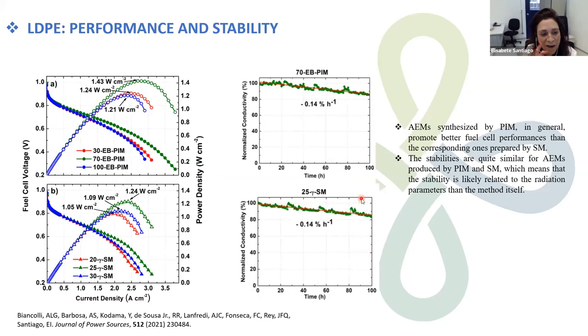So in terms of performance and stability, we have observed better performance for materials obtained from electron beam, I mean pre-irradiation, in comparison to the materials obtained by the simultaneous method. And in terms of stability, we have no significant difference between the methods.